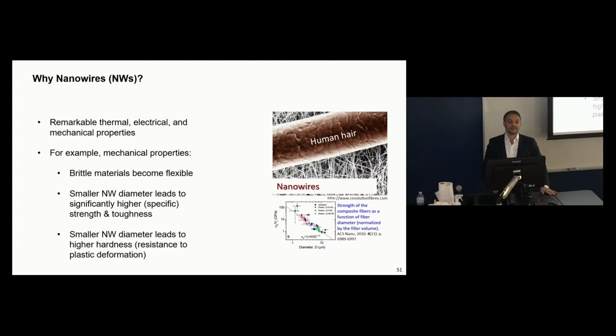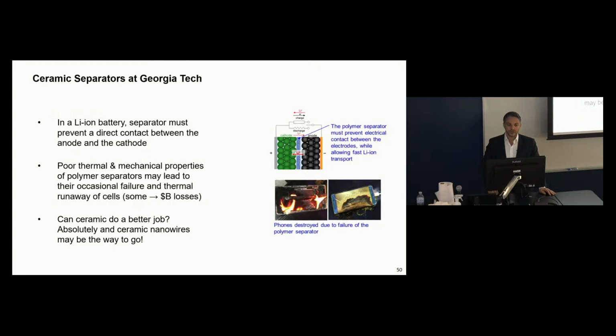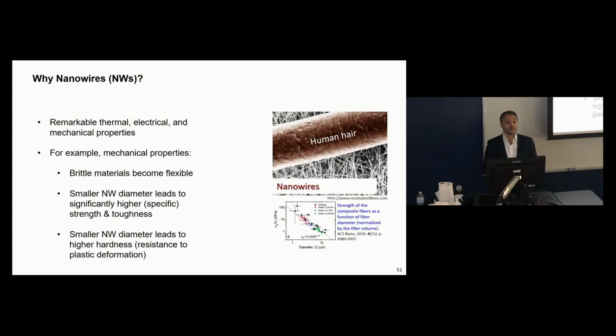And why would nanowires be good? Because ceramic is a brittle material. Bulk ceramic is brittle, right? However, if you have nanofiber formation or nanowire formation, brittle materials become very flexible. And so if you can build ceramic nanofibers, you can overcome these challenges. In addition, if you build fibers, then the smaller they become, the stronger they become as well. So you have high flexibility for small fibers, and they also become much stronger.